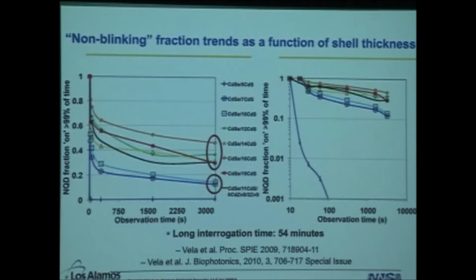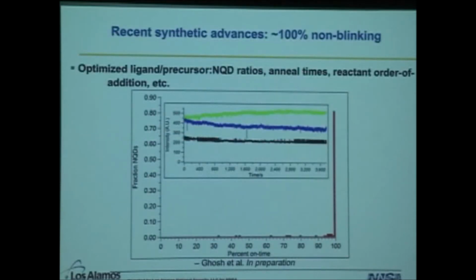And you can see that the fraction that maintains its non-blinking behavior is highest for the thicker shell system. So the 15 cadmium sulfide monolayers, for example, as opposed to 5 and 7, and even 7 and 10. And if you look at the 5 monolayers of cadmium sulfide, there's nothing that's still non-blinking after that observation time. So really the shell thickness makes a big difference.